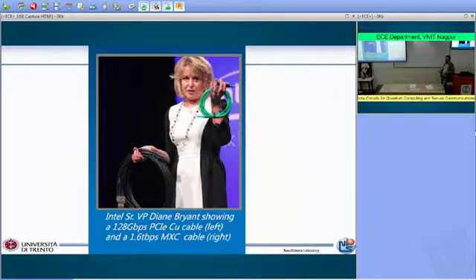So the reason was to try to convince people that these active optical cables, so cables where you have optical fiber and then on the end of the fiber you have a transceiver made by silicon photonics, are actually important for data centers. And what she was demonstrating here is a comparison between a standard copper cable and this active optical cable enabled by silicon photonics. And what you see here is, on one side, the bandwidth, so the capacity. For the copper cable, you have 128 gigabit per second, while for the silicon photonics cable, you have 1.6 terabit per second. So you see the difference in capacity.